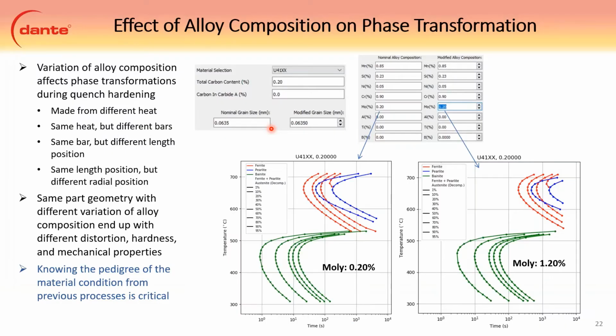All right, so other Dante capabilities. We can consider the alloy composition on phase change. So this example shows if our molybdenum goes from 0.2% to 1.2%, you can see the shift in the ferrite perlite and the bainite noses. So everything goes to the right. So essentially it makes it more hardenable.